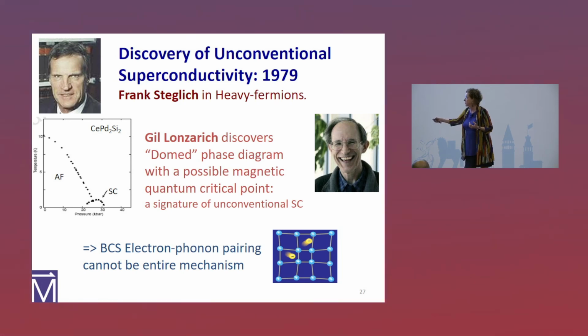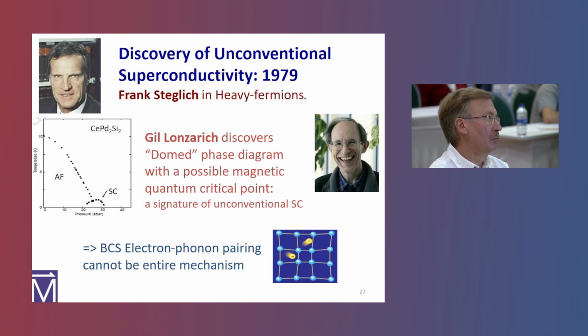And here's the crossover across this line here. And then when you get down to lower temperature, these phases fight each other, which is determined to be a quantum critical point in most of these things, and this dome of superconductivity appears. Why does that happen? Very interesting. But the fact that it's near magnetism, as we all know, conventional superconductors really hate magnetism, right? So why is magnetism all of a sudden good for superconductivity? And it became clear that BCS electron-phonon coupling couldn't be the only story here.